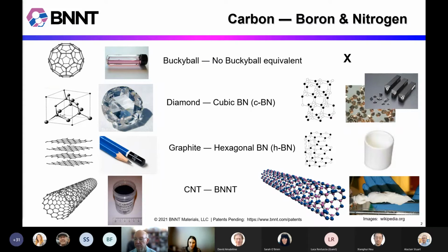They're made of alternating boron and nitrogen atoms and have a corrugated surface. The BN bond is polar in the boron nitride nanotube, which is largely responsible for the difference in properties between the carbon nanotubes and the BNNTs. BNNTs are electrically insulating. They have a band gap around 5.5 eV, which is largely unchanged by the morphology or the chirality of the tube itself.